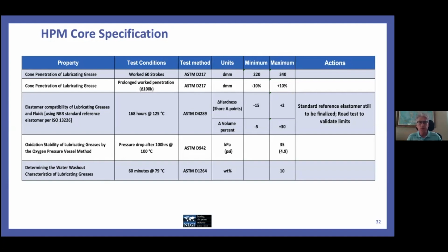And again, this is a test I'm sure many of you are familiar with. Standard condition 60 minutes at 79 C, because the temperature can be varied in this test. And we are specifying a 10% maximum. And you see by the blue shading that this test is part of GCLB today. However, it is 15% maximum in GCLB. So here's an example of a test where we are using a test that is in place currently on GCLB, but we're moving to more stringent limitations.